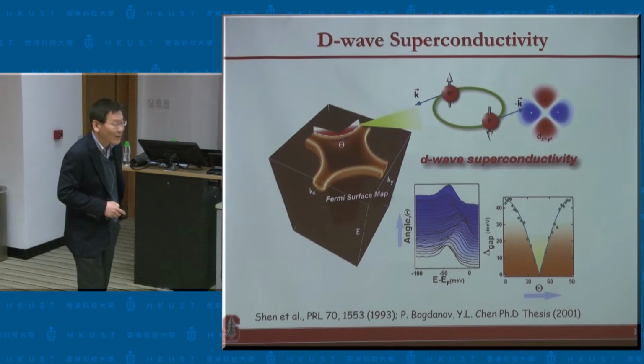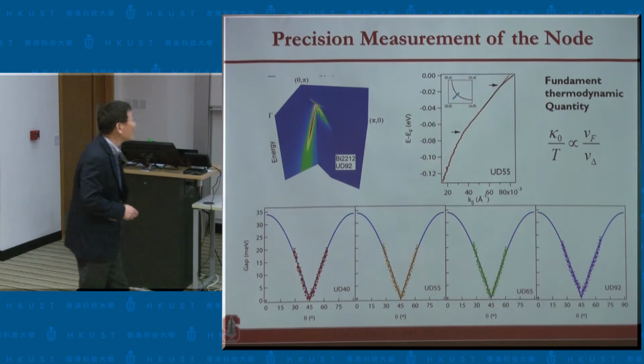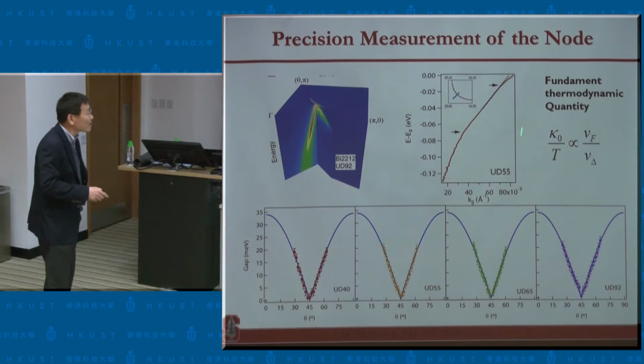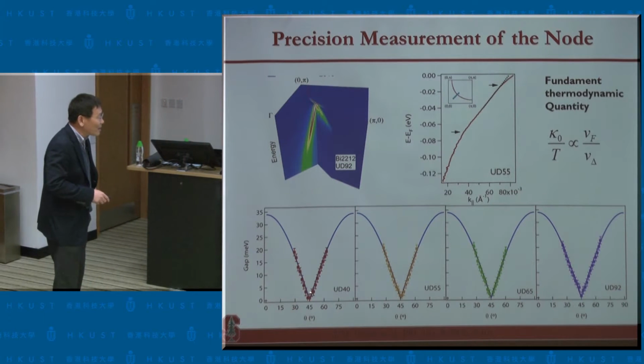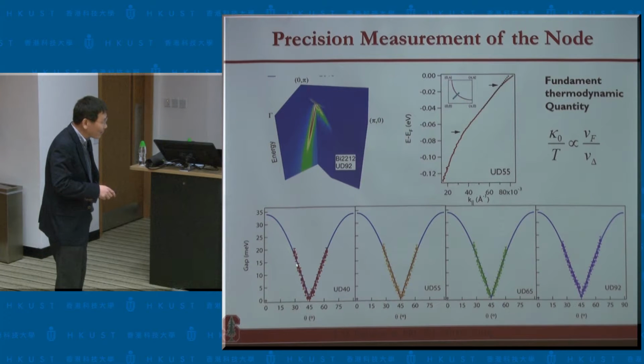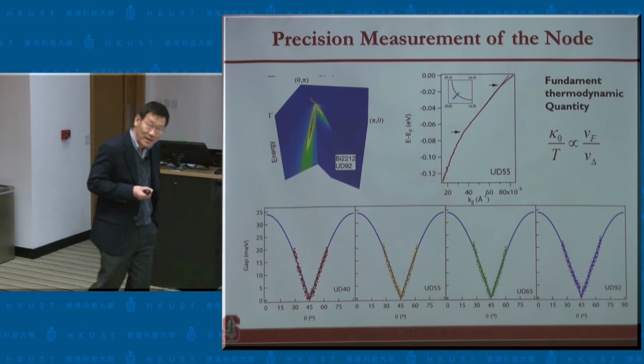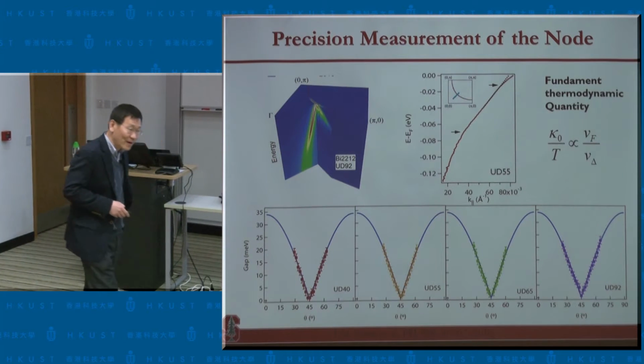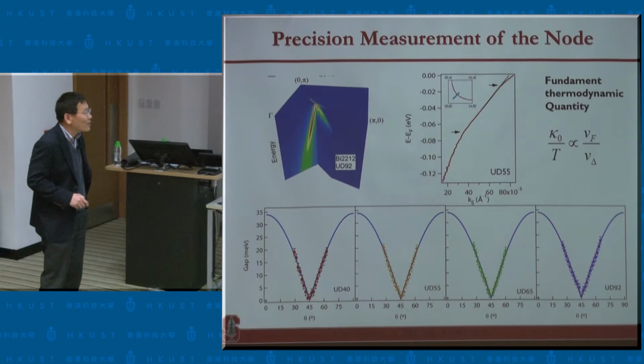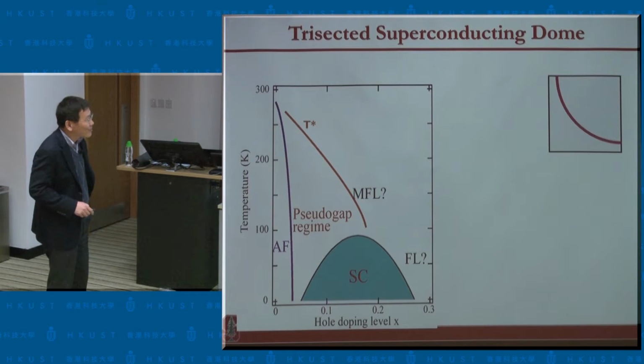So that's what Ina's work is. She did a systematic study, as I indicated earlier. Now she can measure the D wave node. You can see the comparison very concisely. Okay? And as I showed you, the energy momentum relationship will give you a slope. By measuring this slope, you will know the low-lying excitation of the D wave state. Okay. So as a result, she finds this.